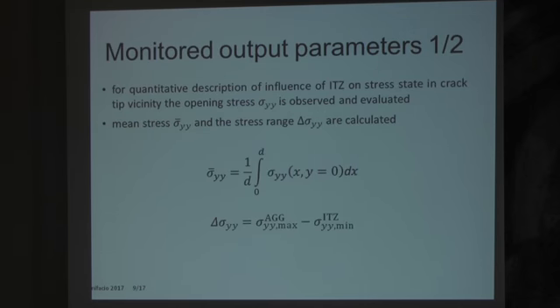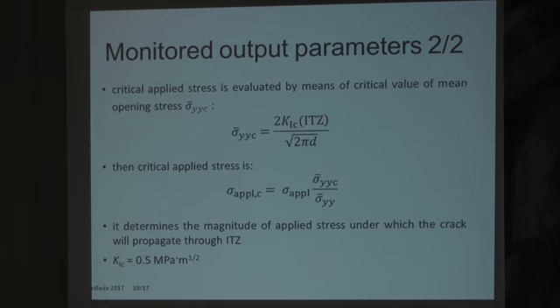Which parameters do we monitor? For quantitative description of the influence of the ITZ on the stress state in the crack tip vicinity, we evaluated opening stresses. It was the mean value of opening stress and the stress range, determined according to a formula. And then we looked at the critical applied stress, which was evaluated by means of the critical value of mean opening stress. The first formula is for the critical value of mean opening stress, and from this we calculated the critical applied stress. It determines the magnitude of applied stress under which the crack will propagate through the ITZ.